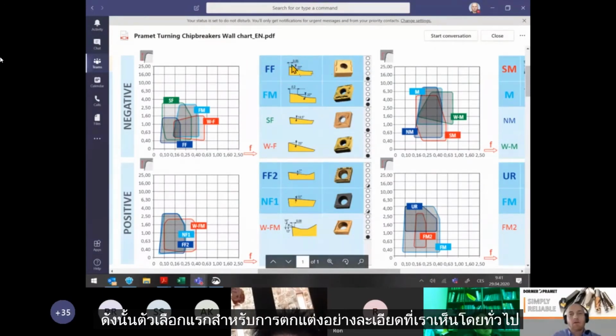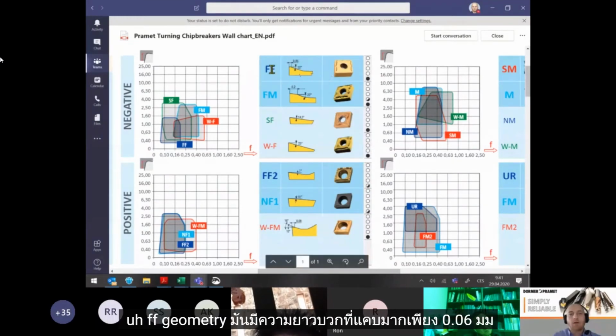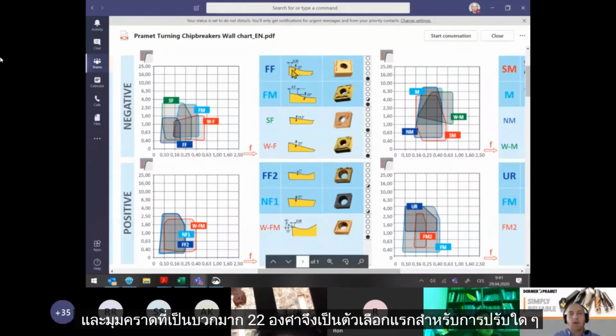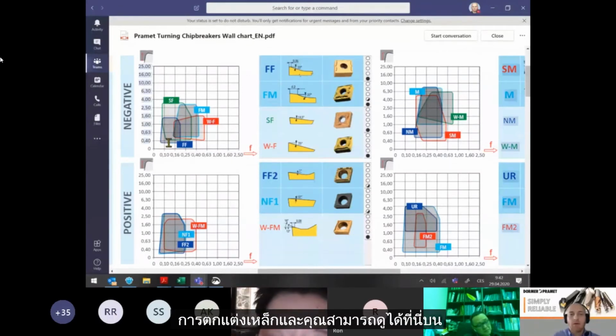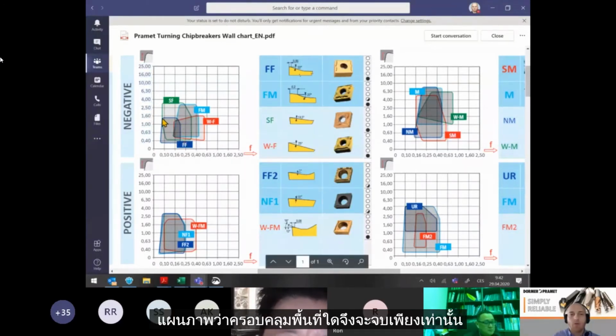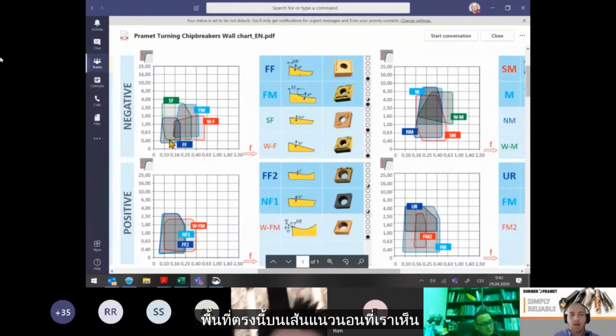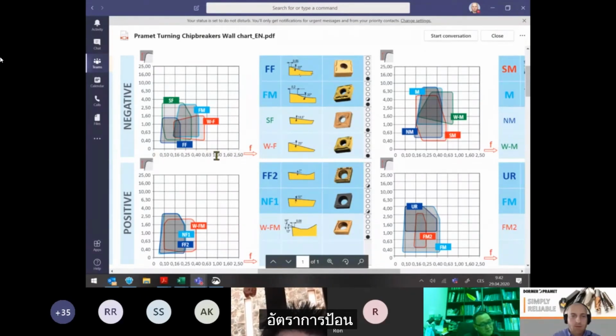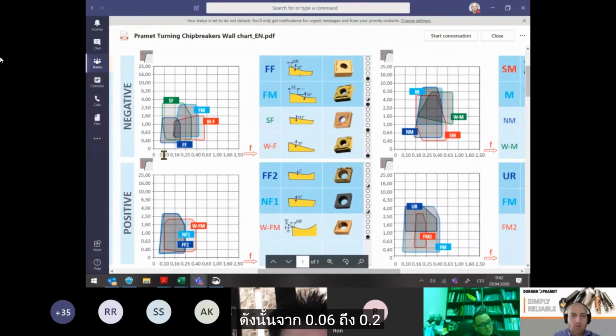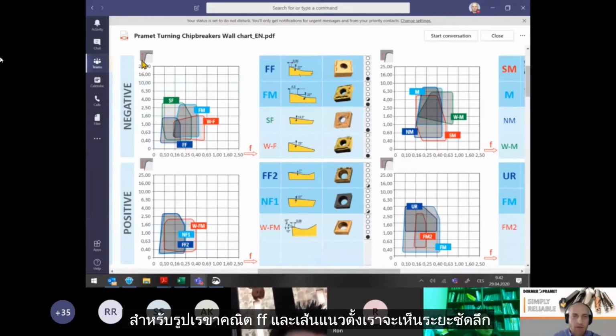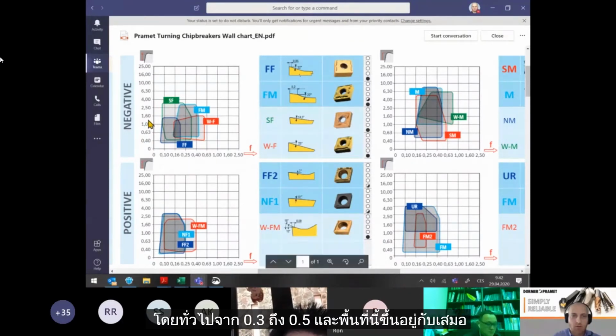So the first choice for fine finishing, we can see, is basically the FF geometry. It has a very narrow positive land length, only 0.06 millimeters, and a very positive rake angle, 22 degrees. So it's the first choice for any fine finishing of steels. And you can see it here on the diagram which area it covers. So only the finishing area. Here on the horizontal line, we can see feed rate, from 0.06 up to 0.2 for FF geometry. And on the vertical line, we can see depth of cut, basically from 0.3 up to 0.5.